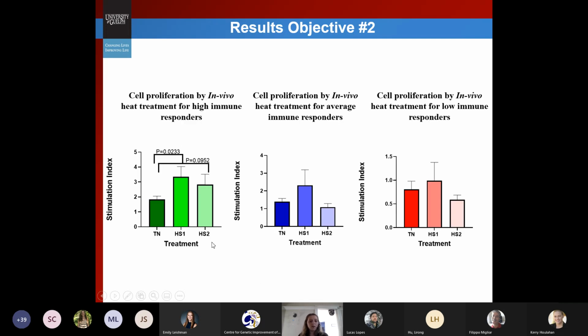And then looking within phenotype across the treatments, again, we're seeing a significant difference or a trend towards a significant difference between the thermoneutral and our heat stress 1 and heat stress 2 treatments in the highs, but then see no significant difference in cell proliferation across the treatments for our average and lows. And studies have also shown that cell proliferation and HSP70 production are actually linked. So these results do correspond with what we were seeing for our HSP70 production.